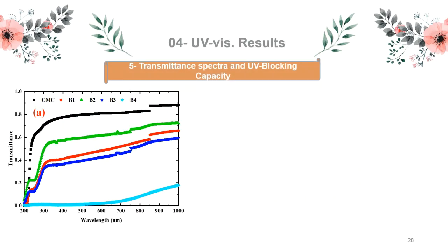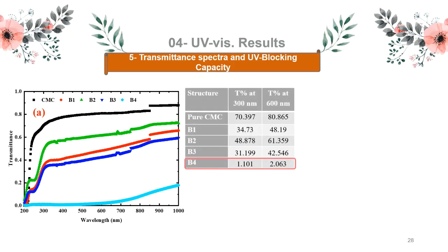The spectral distribution of the transmittance as a function of the incident wavelength was presented in this figure. It can be seen from the figure that the transmittance increases with increasing wavelength. However, increasing the copper oxide nanoparticles concentration decreases the transmittance of the pure CMC. As we can see from this table, the transmittance at 300 nanometers and 600 nanometers decreased sharply with increasing copper oxide concentration until the transmittance reached 1.1% at 300 nanometers for the sample containing 8 weight percent of copper oxide.